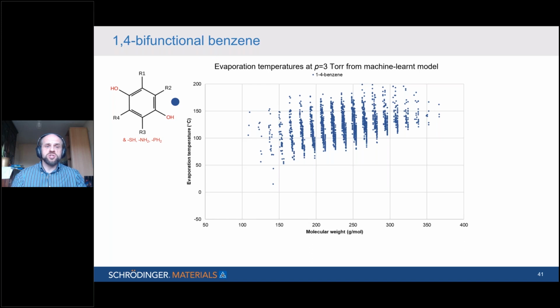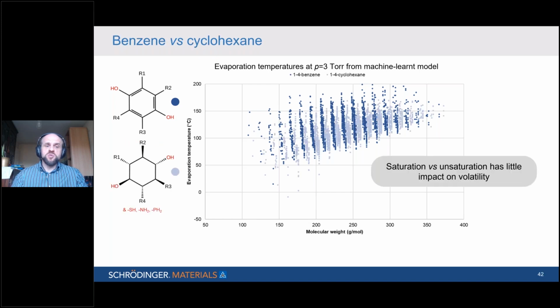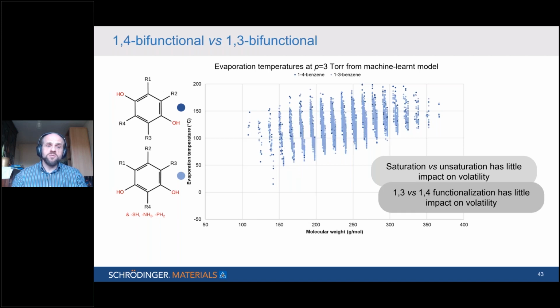Here maybe just to check what happens when we go from the benzene core, which is shown here in dark blue, to the cyclohexane core. And actually the evaporation temperatures change very little. There's just a little shift in mass, as you can see on this graph. So how about going from 1,4 to 1,3 diols and amines and thiols? No difference whatsoever. The 2 sets of data points lie on top of one another.